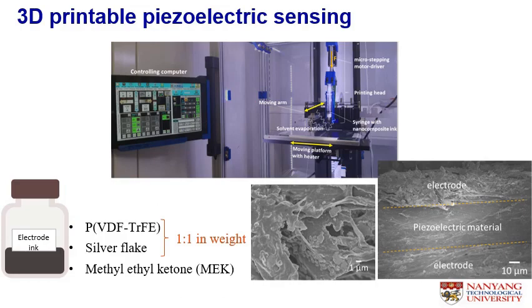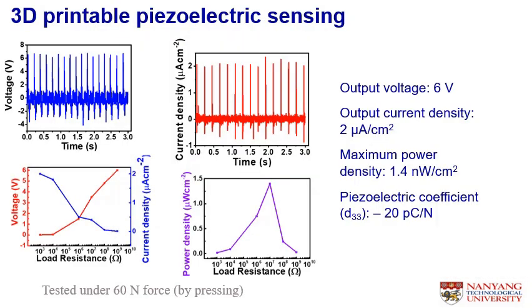In the development of piezoelectric sensing, we have also developed 3D printable ink based on the ferroelectric polymer. The conductive electrode is made of PVDF-TrFE with silver flakes with similar weight ratio in the presence of MEK solvent. The cross-section of the device is shown at the right, SEM imaging. The fully 3D printed piezoelectric sensor provides an output voltage of 6 volt under a 60 Newton force by pressing.